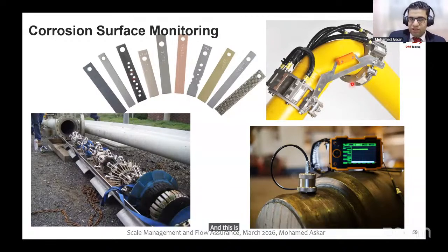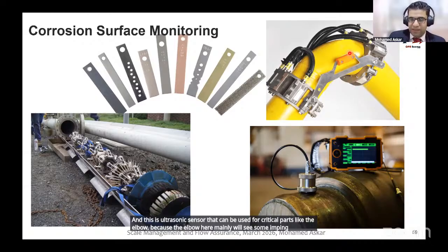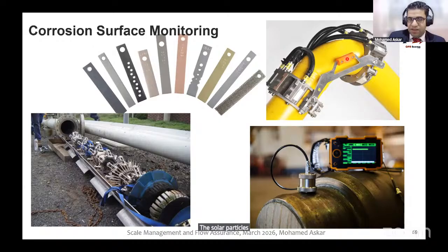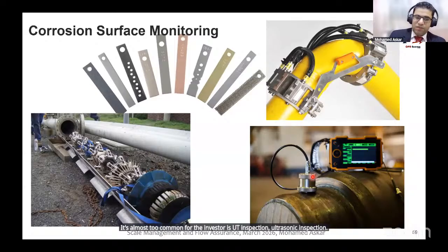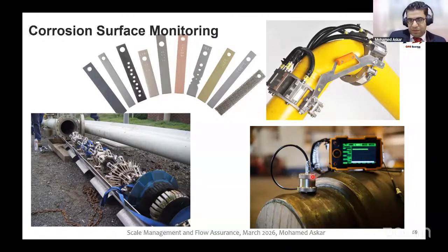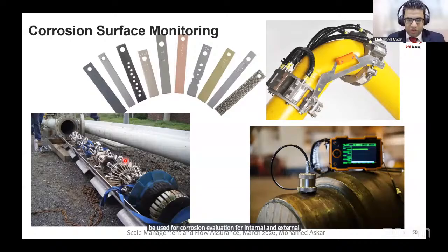And this is an ultrasonic sensor that can be used for critical parts like the elbow, because the elbow will mainly see impingement and impact of solid particles due to solid production and sand production. The most common in the industry is UT inspection, ultrasonic inspection. Some service companies get to the flow line and can be used for corrosion evaluation, for internal and external corrosion of the flow line itself, especially for inaccessible flow lines.